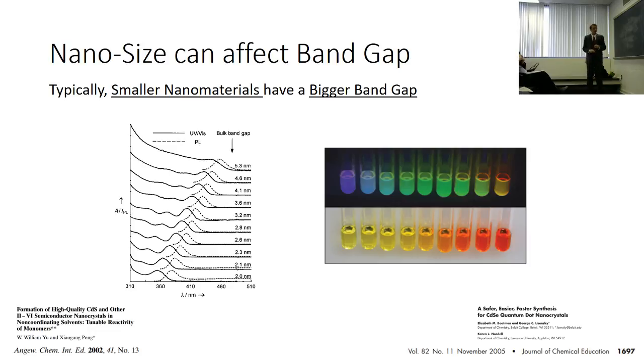Here are two examples of nanomaterials: cadmium sulfide and cadmium selenide. When you get down to the nanoscale, size matters a lot in terms of properties. These researchers changed the size of cadmium sulfide nanoparticles and measured their UV-vis and photoluminescence — ways to measure band gap. It equates to changing color essentially. So you change your color, change where you emit, change where you absorb light, change your band gap.